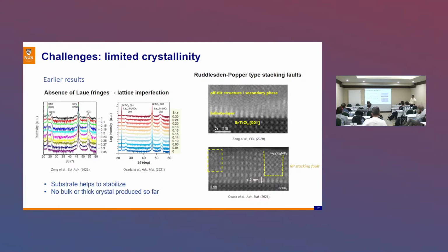So what we are able to do now is really based on three things. We look into the so-called Laue fringes in the XRD, and then using high resolution STEM, we try to confirm. Of course, this is going to be a very slow process. As you are aware, STEM is a very tedious thing to do. And then, of course, resistivity is another hint that we can use to judge the quality of the samples, whether we are going to be able to produce superconductivity or not.